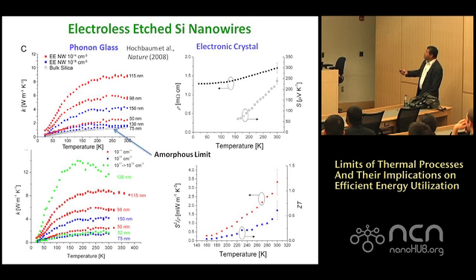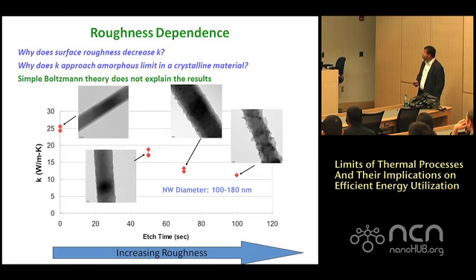The question is, why does the thermal conductivity go down, and is this really true? Does the roughness really control the thermal conductivity? And we did many other experiments. So the questions are, why does surface roughness decrease K? Why does K approach the amorphous limit in crystalline material? Simple Boltzmann theory does not explain the results here. And this is thermal conductivity as a function of etching time, which controls roughness.